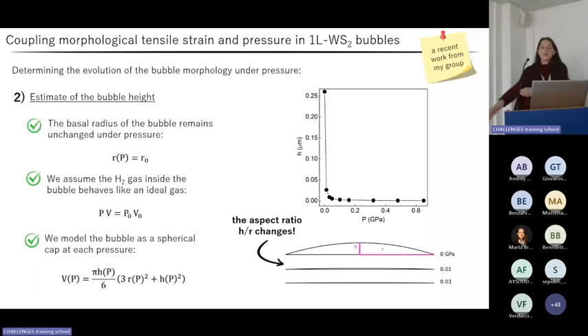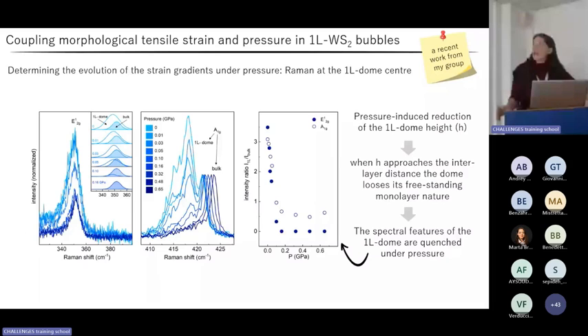Okay, now let's have a look at the pressure evolution of Raman and photoluminescence spectra collected at the dome center. In the Raman spectrum, the first thing we notice is that the intensity of the monolayer contributions dramatically decreases under pressure. This may be related to the decrease in the bubble height, which determines a progressive reduction in the interlayer distance between the bulk and the dome, making the latter progressively lose its freestanding monolayer character.